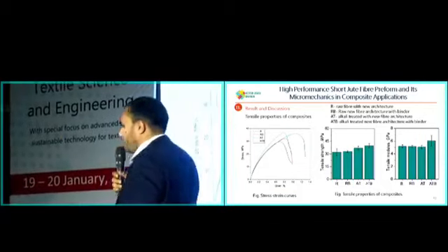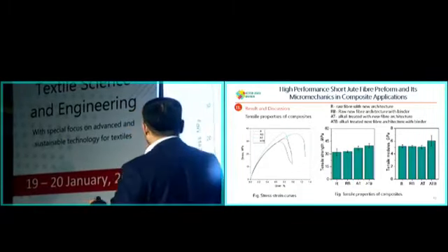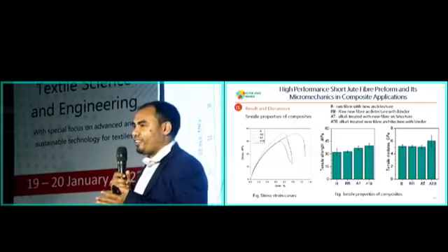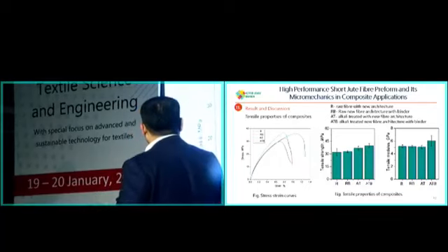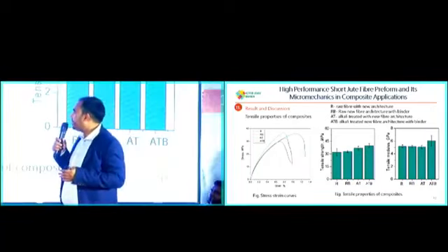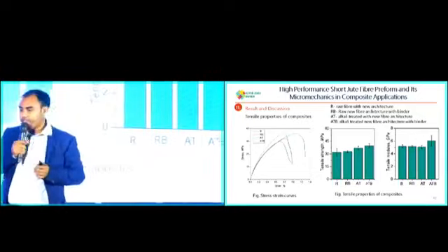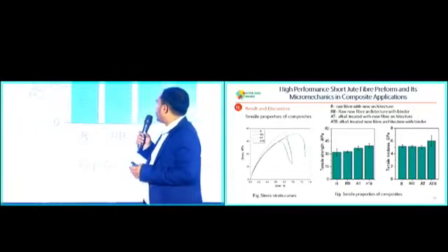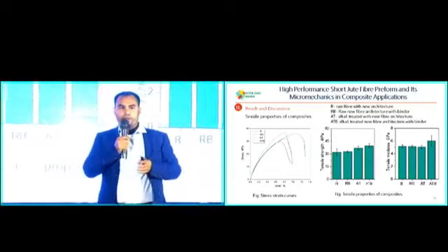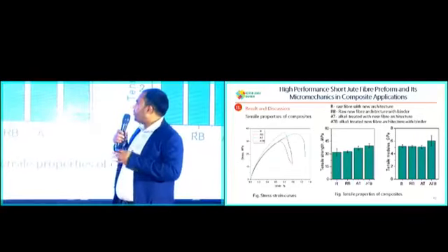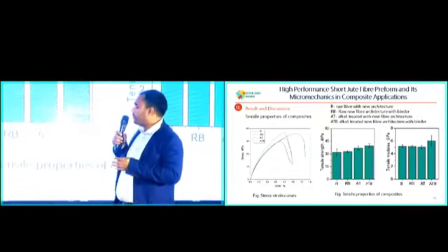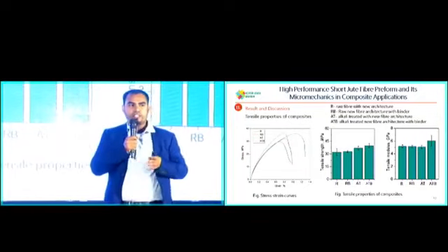From the curve, you can see the composite is not brittle like monolithic materials or metals. It shows a little bit of viscoelastic behavior, and this is the beauty of composite materials. As you can see, the raw jute fibers that we developed in our laboratory with the new fiber architecture don't give that kind of mechanical properties, with a tensile strength of only 28.